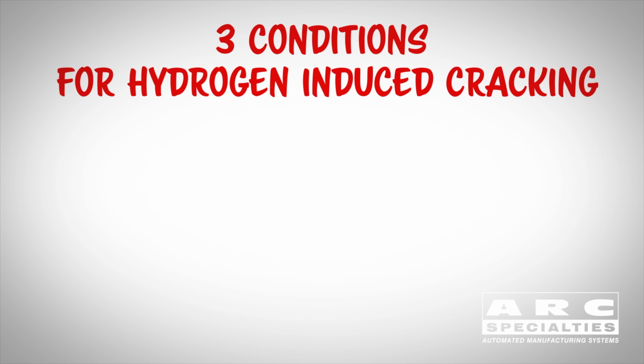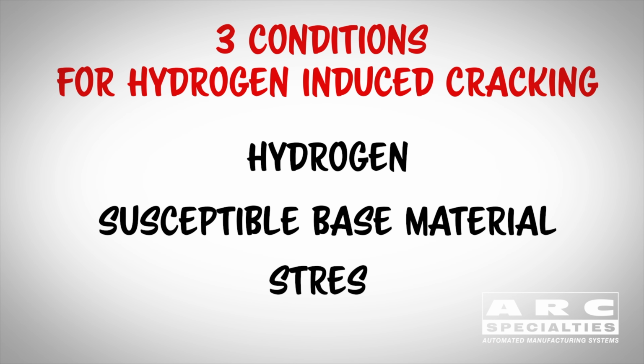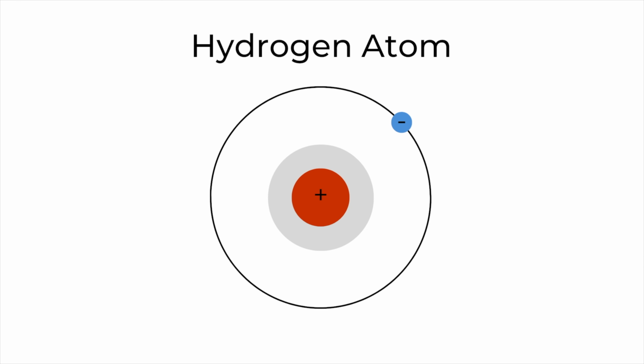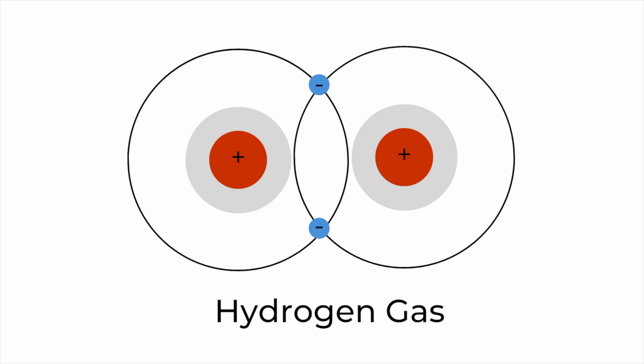The three conditions which are necessary for hydrogen-induced cracking are hydrogen, a susceptible base material, and stress. Without all three of these conditions being present at the same time, you'll not experience hydrogen-induced cracking. And I'll go on to say that the hydrogen must be atomic hydrogen, that's just H, which is why hydrogen gas, which is H2, can be transported safely in high-strength pipelines.